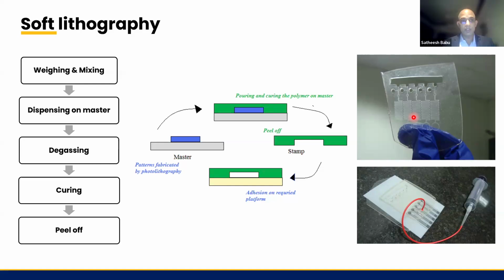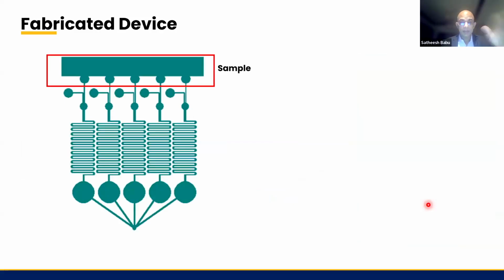So for the soft lithography, on top of the negative that we fabricated by the photolithography process, we poured the PDMS, then baked and then peeled off. Then it is stuck on a plastic substrate such that we were able to make a simple microfluidic system, and then we connected it using a syringe so that by applying negative pressure, we were able to make the fluid flow. And this is how it looked.